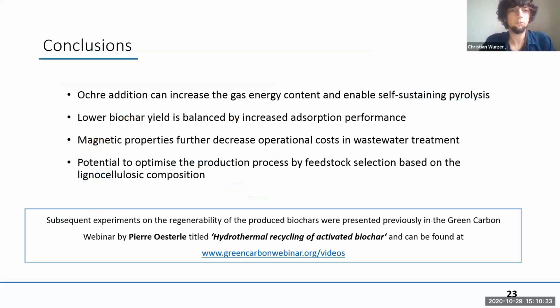So as conclusions, we showed that ochre addition can increase the gas energy content and enable self-sustaining pyrolysis. That's often an overlooked part of iron doping, that you usually only look at the performance of the solid product and not at the process itself. And the lower biochar yield is balanced by increased adsorption performance, although an optimization of the activation parameters is necessary to actually produce this efficiently.